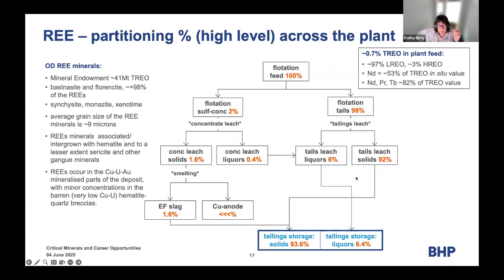When we look at the endowment for the total rare earth oxide at Olympic Dam, it's quite high. Bastnäsite and florencite are the dominant ones. But we know by doing all these measurements on plant composites over 2 decades plus, and doing very detailed mineralogy across the ore body, that the average rare earth grain size is less than 9 microns. Now, you process engineers get that, that's not a trivial thing to go after.